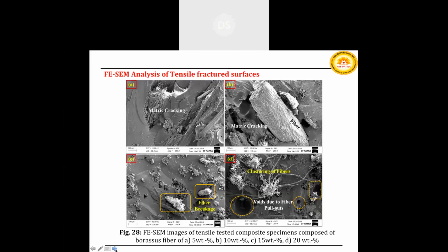In 15% borassus fiber weight ratio, as increased, the tensile strength was found higher as a result of a strong bond between fiber and matrix, as the crack could not propagate freely due to the uniformity of the fibers in every direction, and the fibers were able to bear the load.